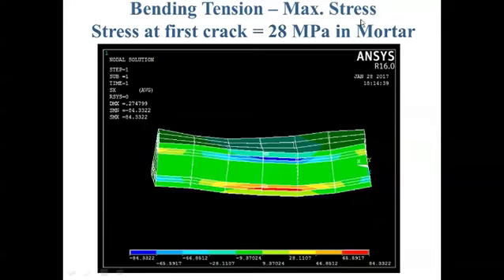This shows the deflection pattern and what happens exactly at the jali, and the stresses induced, depicted by different color codings, each representing a specific stress value. We observed that the stress at first crack was almost 28 Newton per mm square in the mortar, and as loading increased, the crack propagated towards the neutral axis, and we could get the ultimate load carrying capacity.